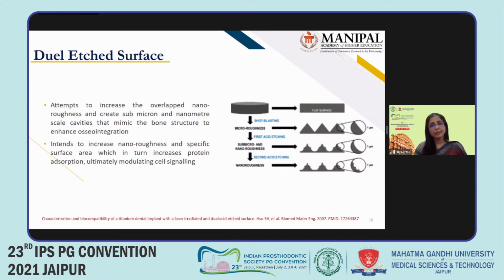Now, going on to another surface, which is also an acid-etched surface. This is called the dual etch surface. Dual etching is basically done to roughen the implant surface by immersing the titanium implants for several minutes in a mixture of concentrated hydrochloric acid and sulfuric acid, and it's not just immersed in the acids, but also heated above 100 degrees Celsius. The dual etching creates a specific topography which enables them to attach to the fibrin scaffold, thereby guiding the migration of the osteoblast onto the surface. The dual etch surface intends to increase the nano roughness and the specific surface area, which in turn is supposed to help in increasing protein absorption and ultimately modulating cell signaling.